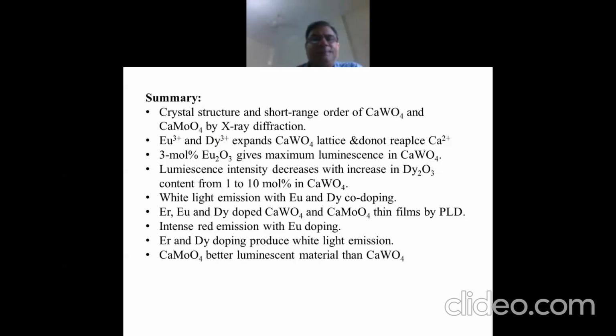Luminescence intensity decreases with the increase in dysprosium oxide concentration from 1 to 10 mole% in calcium tungstate. And you get white light emitting materials which can be used for fabricating white light LEDs by using europium and dysprosium co-doping.